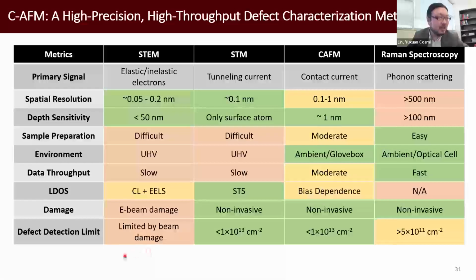Another comparison is about the defect detection limit. The first three can detect a wider range, especially if the defect density is very low. The last one, Raman, is an optical approach, and it detects phonon scattering. If the defect density is low, the defect-related Raman band will be too weak, so it can only be good for detecting material with higher defect density.